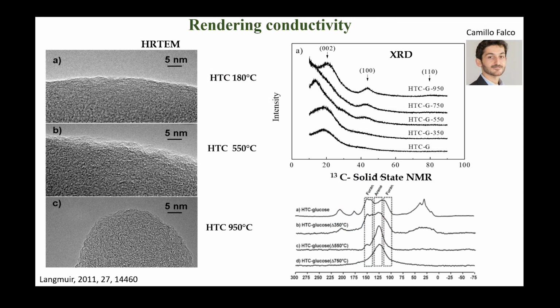Now, on how you make them conductive, as I said, you can make them at temperatures as low as 180. At this temperature, I showed you that they are carbonaceous materials. They have all these furans, some aromatic groups, some aliphatic groups, some oxygen functionalities. So they're quite heterogeneous in their structure and not very conductive.